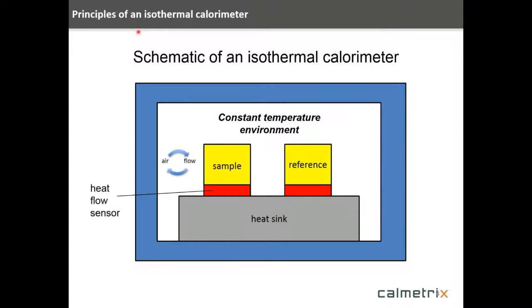Let's first talk about the basic principles of an isothermal calorimeter. Here you see a schematic of an isothermal calorimeter, and let's start on the inside with the sample and the reference. The sample in our case sits inside of a 125 milliliter sample cup. These are reusable sample cups. We'll talk about those in a little bit. And then we run that against a reference material. This is typically a metal material, something that has no reaction as we run the experiment.